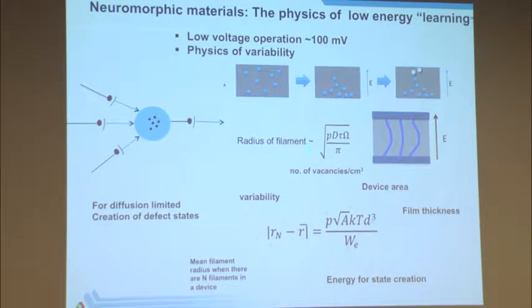But if you use a simple concept of a resistive state being changed, in this case, let us say, by a filamentary formation of a line of vacancies, or it could be, let's say, some solute atoms that form a filamentary line. If we assume that this is diffusion limited, okay, then one can do a very simple back of the envelope calculation to show that the variability in the resistance of this device is going to be inversely proportional to the energy that you need to impart to the device to change its state. Which means the lower the voltage, the higher the variability.